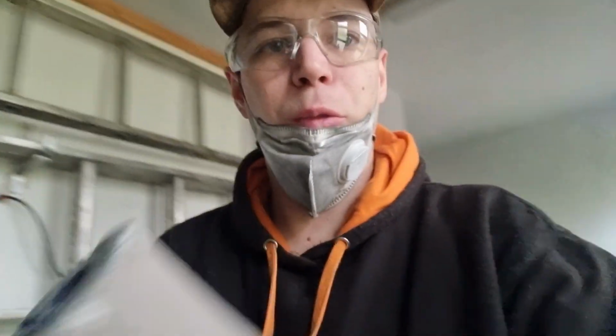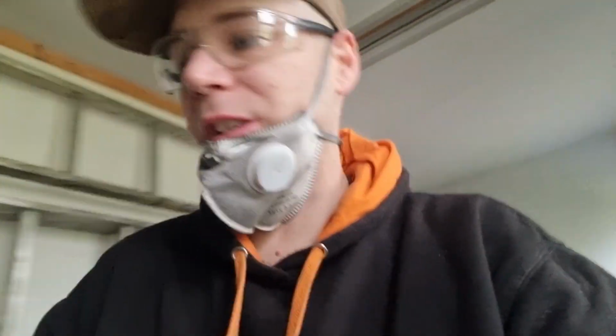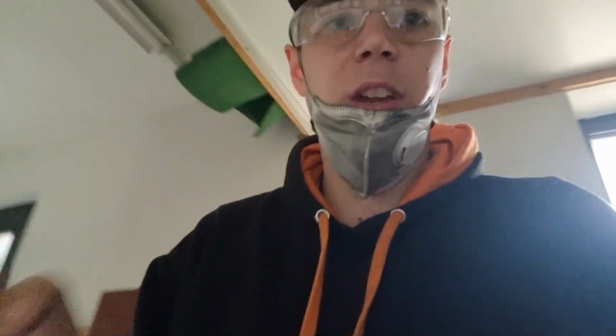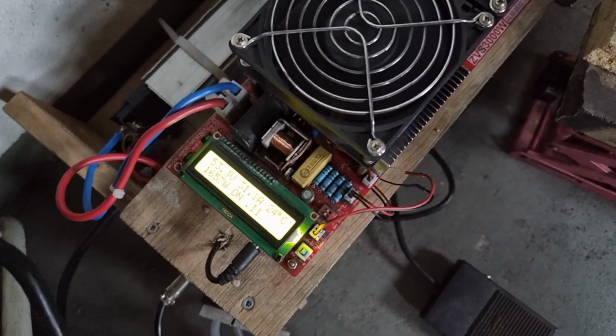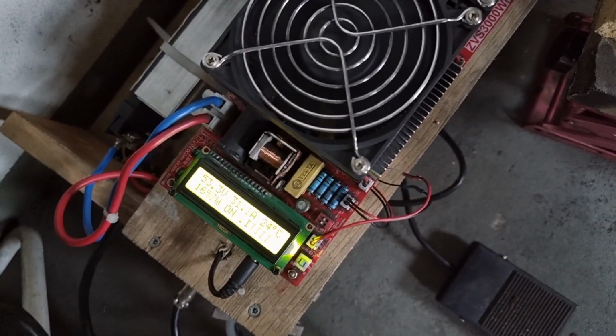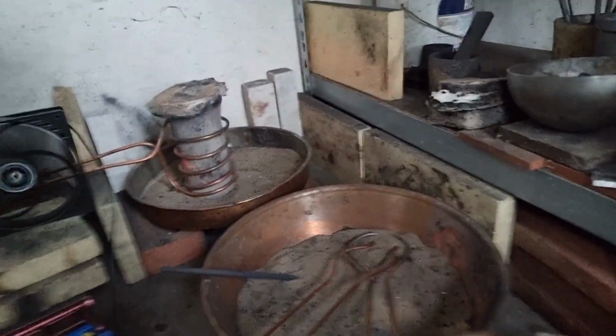Such a 3 kilogram graphite crucible is going to last for 6, 7, maybe 8 smelts, if you're lucky. But then the walls start to get weaker and thinner, and at some point you're going to end up with some holes here. So let's see. The wattage, the power, dropped here to 1600, so that seems to be almost ready for extraction. So in a second.